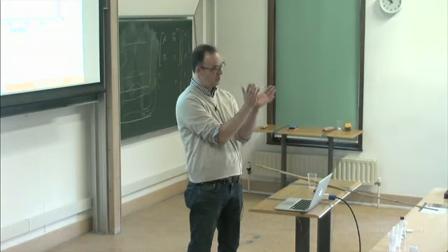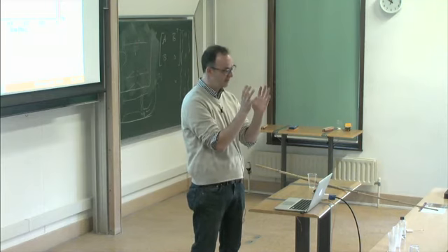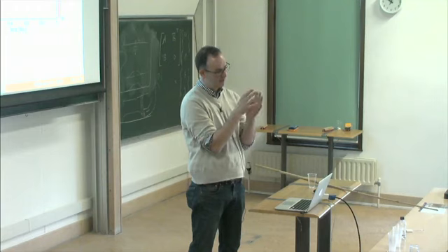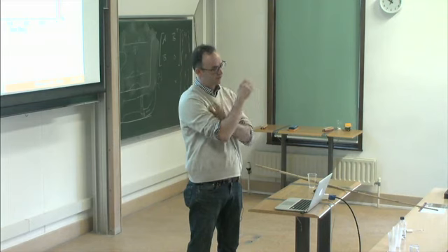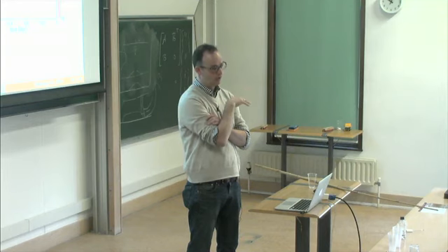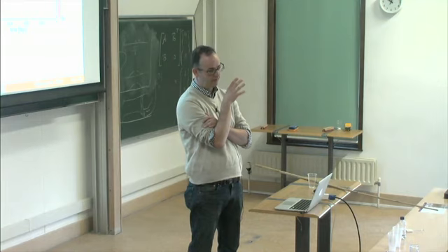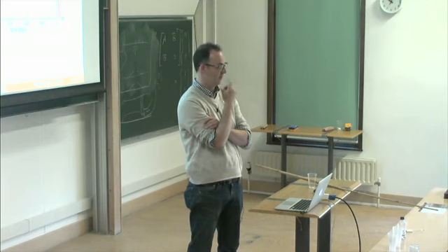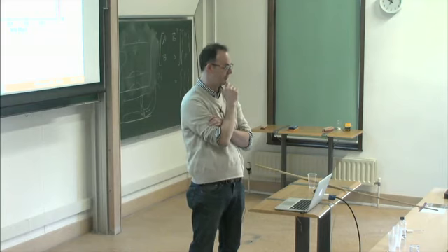they're extremely thin, and you can see very nice dihedral angle type features. So I'm not really sure how that's related. I'm not sure what the volumetric change is as you melt the iron. Maybe there's an actual volume change on the whole thing, and that's just a fact of trying to accommodate that. Again, I'm not arguing that this is happening in all possible planetesimals. I'm just saying there is a hopefully physically self-consistent way that you could segregate iron without either entirely melting it or totally destroying it with a shock. And that doesn't mean those things couldn't happen, right?